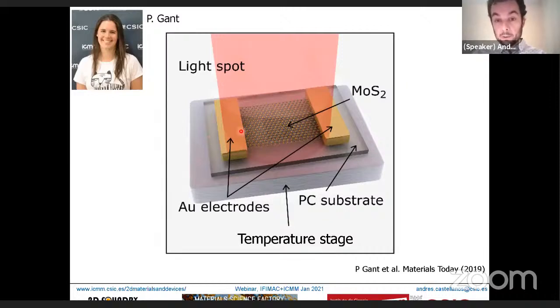So basically the measurement is the following. We have these two electrodes, and we have the molybdenum disulfide channel. We apply a bias between the electrodes and we measure a current. Upon illumination, we might generate photocurrent, so we will have an excess of current, and that was what we monitor in our measurement.